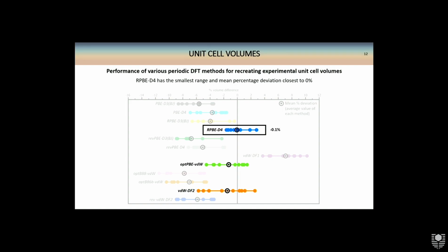On the whole, this RPBE-D4 functional we found to be the best performing DFT method. Not only did it have the smallest range over which the results were spread, but also the mean percentage deviation is incredibly close to zero, just 0.1% off.